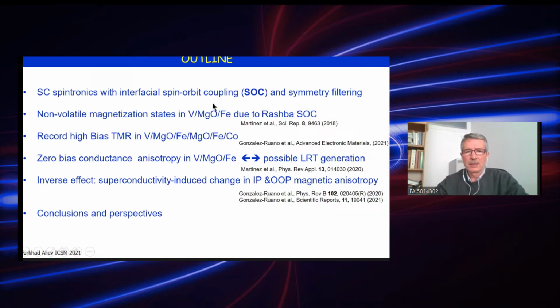Our work is basically the first experimental study of fully epitaxial superconductor-ferromagnetic structures, coupled through a Rashba-type spin-orbit coupling, with symmetry filtering. As I will show, symmetry filtering in the presence of spin-orbit coupling allows us to introduce a current which is mostly affected by the presence of spin-orbit coupling. Also, the system we investigate has the ability to create non-volatile magnetic states.